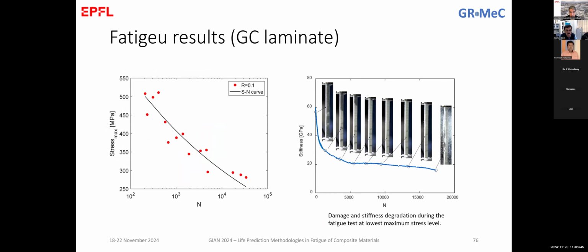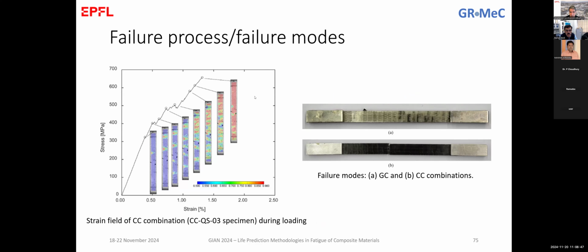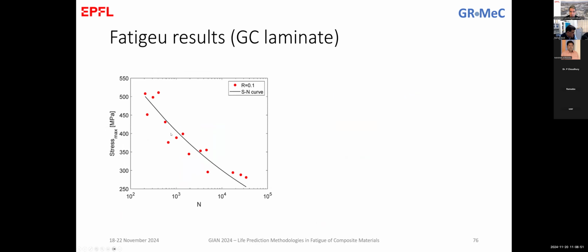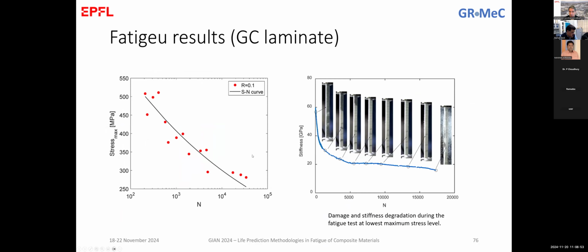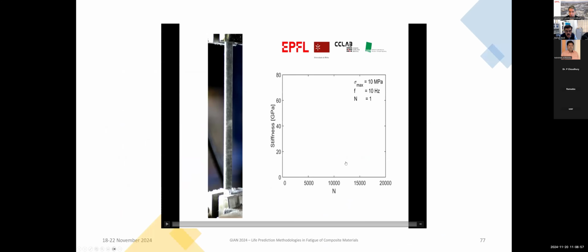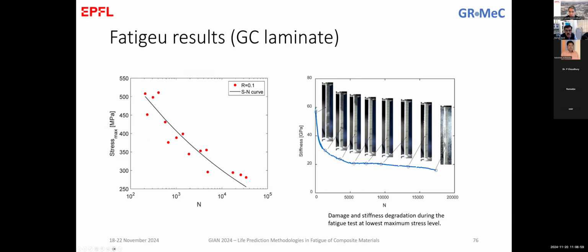So until now we were discussing static loads, quasi-static loading. When we go to fatigue loading, again we observe the stiffness. Sorry, I will show this again. We observe the typical stiffness degradation. Again here, if you see in fatigue, stiffness drops.